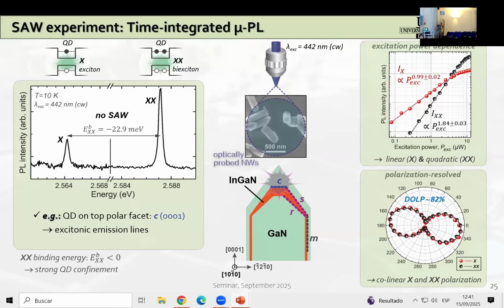This exciton-biexciton assignment here is corroborated by the excitation power dependence measurements, which, as you can see here, show a linear increase for the case of exciton and a quadratic increase for the case of biexciton of the integrated peak intensities as a function of optical pump power. Additional confirmation is provided by polarization resolved experiments, and they show that these two lines are collinearly polarized, as you can see here, and they exhibit the same degree of linear polarization, which is what we actually expect in the case when exciton and biexciton are emitted from the same quantum dot potential.